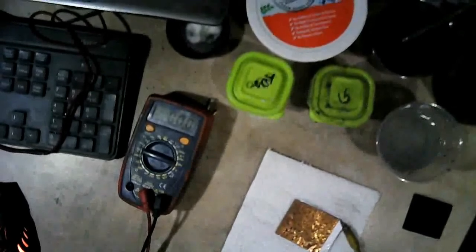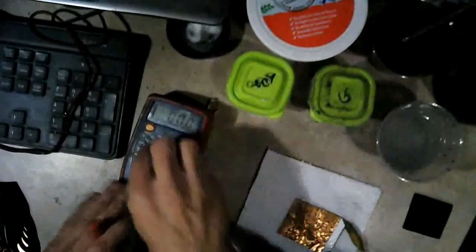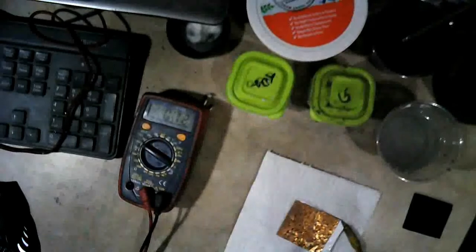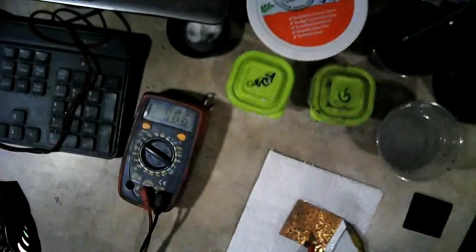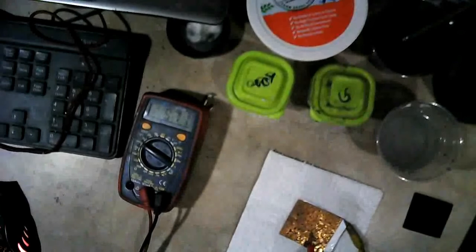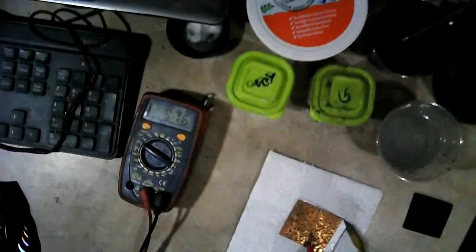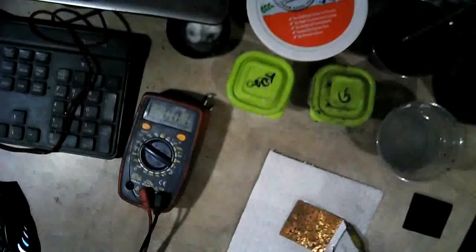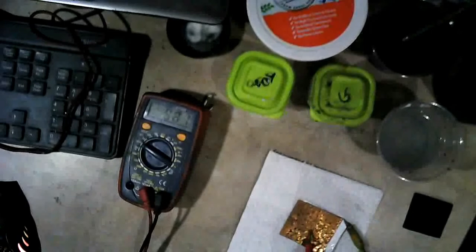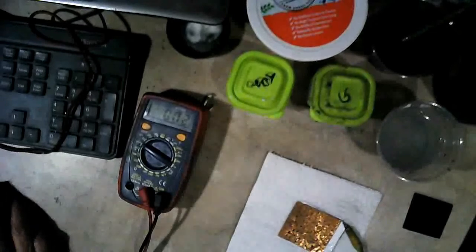That's as simple as it gets now, and that one might turn out to be really good. Let's discharge it a few times and find out. Let's see what kind of self-charge it's got. That's as good as we got with two coats of graphite on the thing before. We're already back to 0.96 and it's still climbing pretty fast. So that's a good self-charge too. The air definitely makes a difference. We've got minimal things stopping the air from getting through and oxidizing that zinc plate.